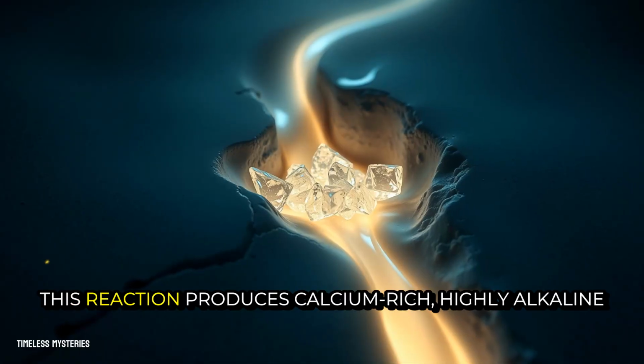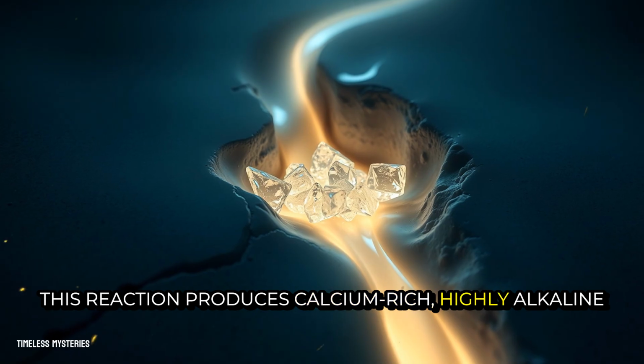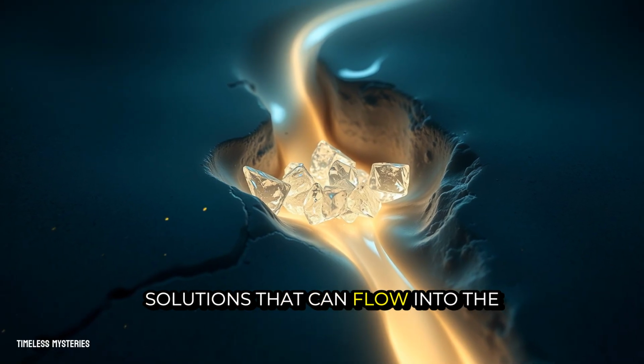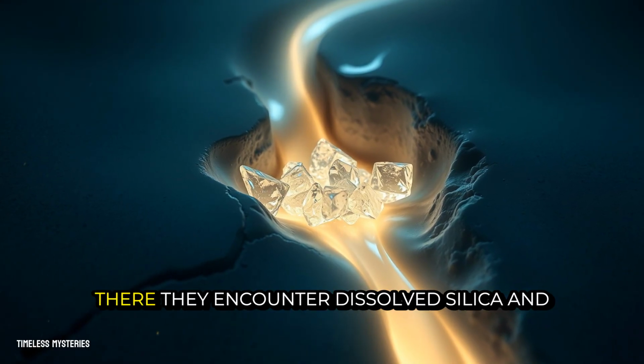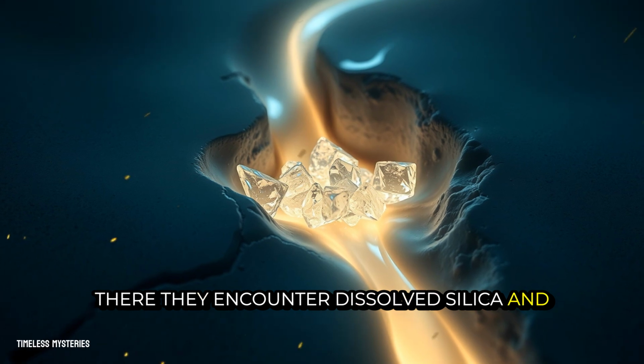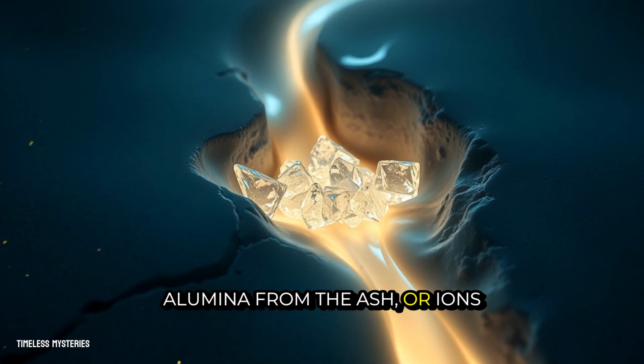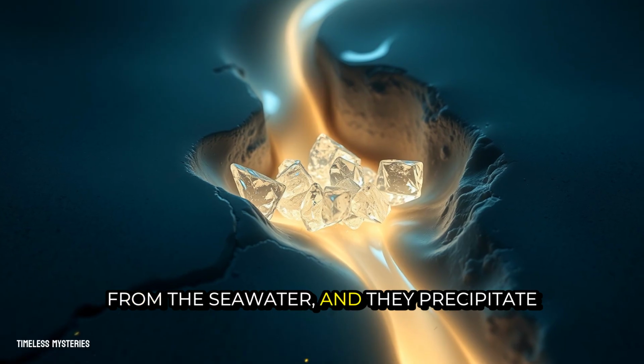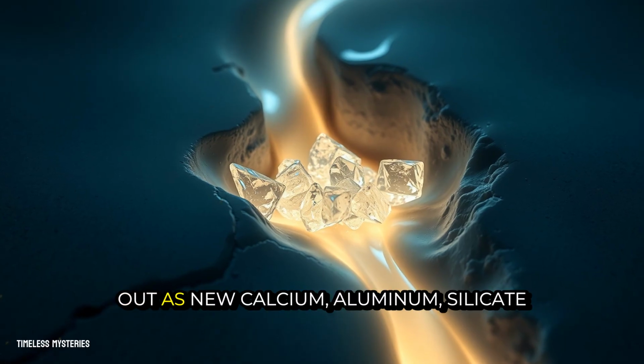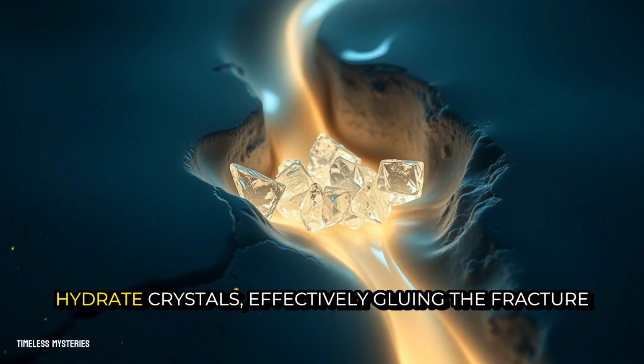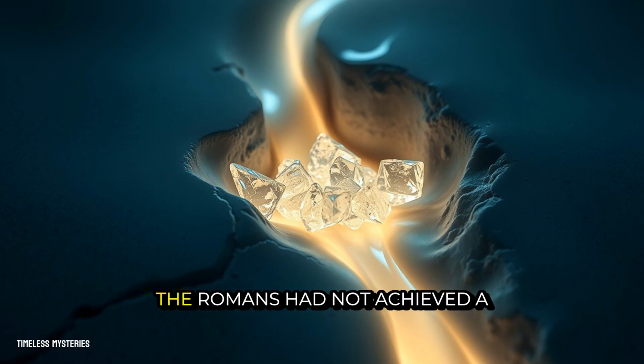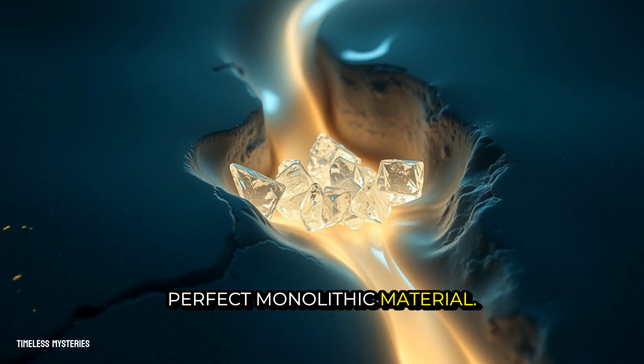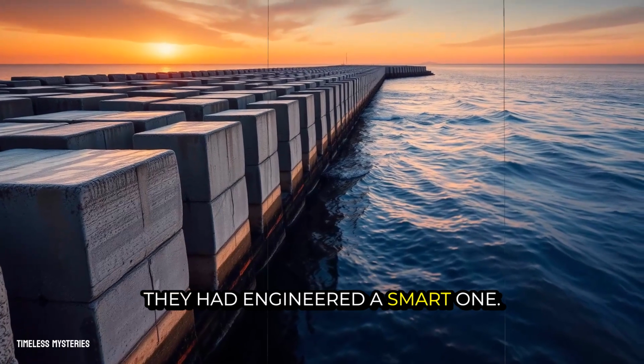This reaction produces calcium-rich, highly alkaline solutions that can flow into the crack. There, they encounter dissolved silica and alumina from the ash, or ions from the seawater, and they precipitate out as new calcium-aluminum silicate hydrate crystals, effectively gluing the fracture shut. The flaw was a self-healing mechanism. The Romans had not achieved a perfect monolithic material. They had engineered a smart one.